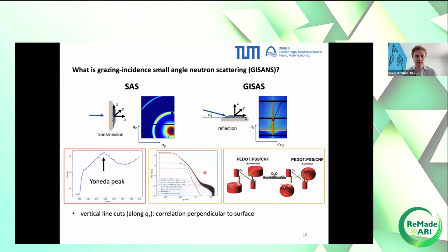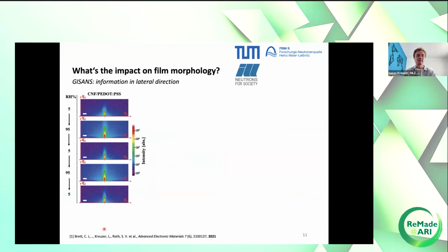If you do this at the Yoneda position, keep in mind that you are rather surface sensitive. If you want to be more bulk sensitive or extract the morphology from the bulk of the film, then you can go to higher QZ values where you are more bulk sensitive. But with these vertical and horizontal line cuts, you get morphological correlation perpendicular and lateral to the surface, to the substrate or the film surface. And this is what we also did with our films.